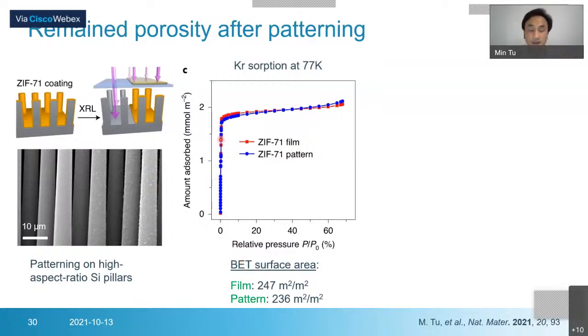Based on the krypton adsorption isotherm, we calculate the film surface area is around 250 square meter, but here we don't know the mass of our MOF film. We only know the area of our MOF film, so we have the unit of square meter per square meter. After the patterning, we can selectively remove certain parts of the MOF film. You see this is very clean, and this is our MOF film. We did the krypton sorption again and did the calculation for the MOF pattern. We have around 236 square meter per square meter. So we can confirm that the porosity remained, with maybe very slight changes.